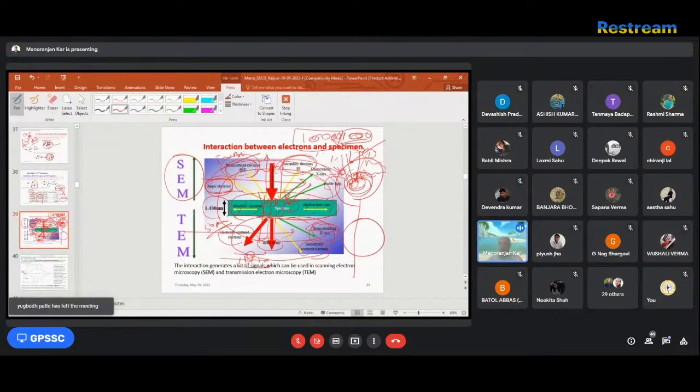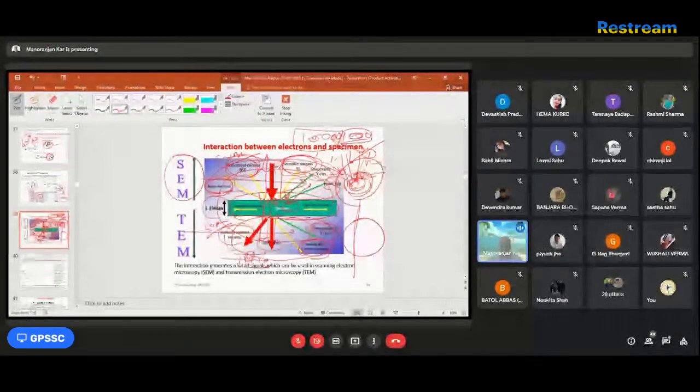We have the Auger electron microscopy. We have the backscattered electron microscopy. We have secondary electron microscopy. We have X-ray detection. We don't bother about the visible, UV, etc. So then here we use the elastic scattering electron and inelastic scattering electron. I told you that, while they go through this potential, they will lose energy. So I can compare this inelastic scattering with the incident electron, then I can find out how much energy it has lost. That really depends upon the chemical environment of the element.